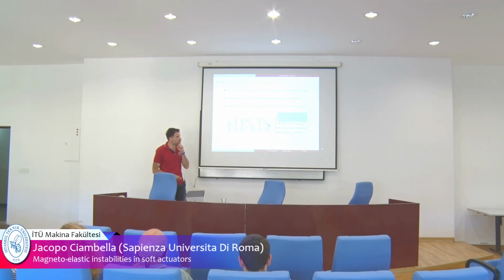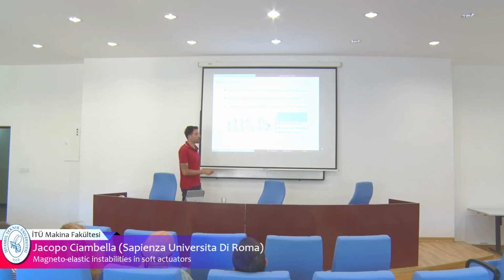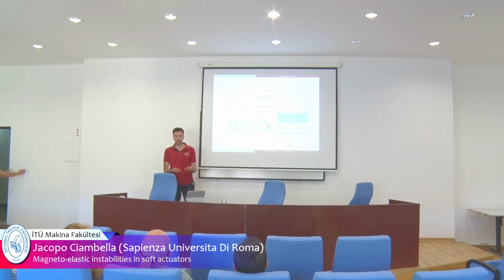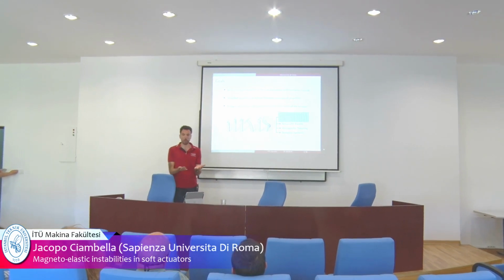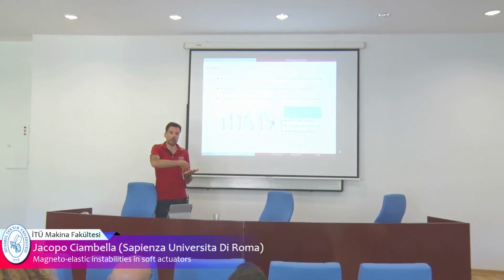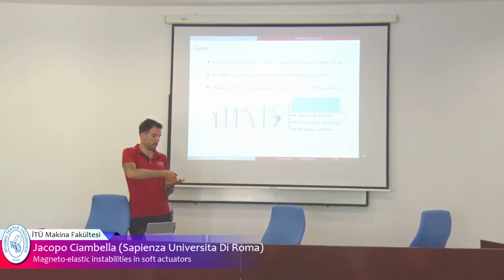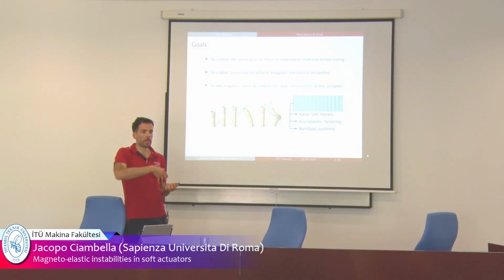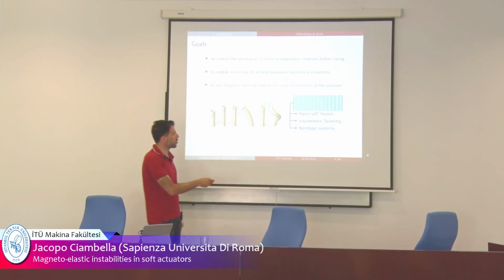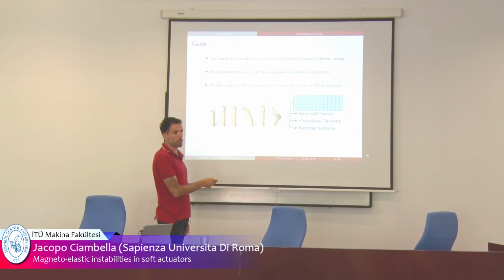And this is reminiscent of what we are trying to do here, and of what is normally carried out in standard composite material, epoxy-based composite, with a technique which is called VAT. VAT stands for variable angle tow. So they have this technique where in epoxy-based composite, they're able to steer the fiber within a plane, within a ply of the composite, with an external machine. And so they do something like that. They start with a certain orientation, and then at the other side of the specimen, they obtain an orthogonal orientation.